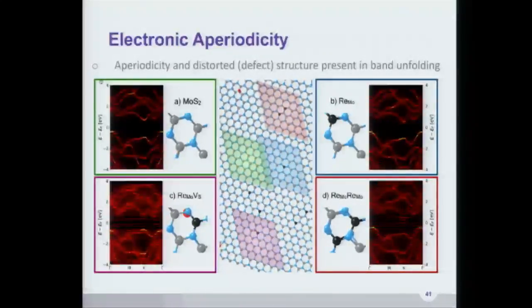So they have a flake. It has about 2,000 atoms. They give us the atomic coordinates, okay? And the atomic coordinates, by the way, are not just in 2D, but also in 3D, which is important because that's where you see that Z variation and the fact that there are long-range ripples and all of that good stuff.